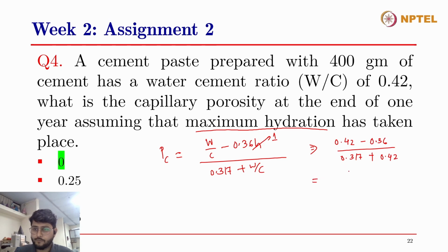Now we know that the maximum hydration has already taken place, so H tends to 1, right? So that will give us, for a water to cement ratio of 0.42, PC equals 0.42 minus 0.36 divided by 0.317 plus 0.42. Can somebody calculate this and tell me the answer? The answer comes out to be 0.08.